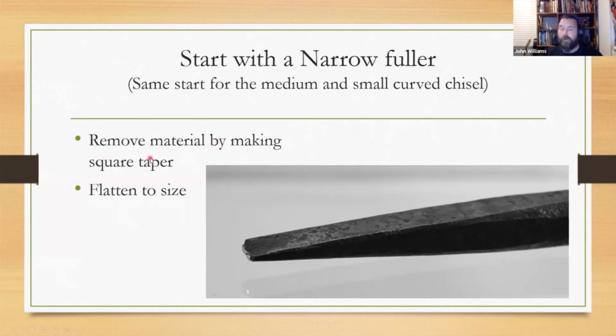In other words, you're going to forge the end so that it's a smaller cross section, because steel forges best when it's compact and it has a good relationship, like say a 1-to-1 ratio between its width and thickness would be the same size. And then by the time you get above 3-to-1, if you were to hit these thin edges, you might cause this edge in here to buckle. And that's more important on tool steel too, because if you have buckling in here, you can actually propagate some cracks by forging on real narrow edges. So you want to keep things square until you take it to a flat.